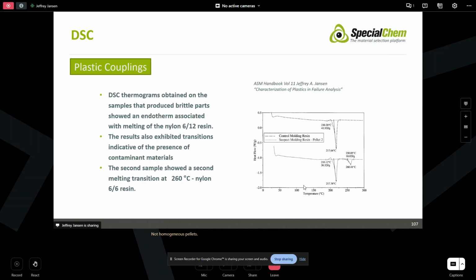We ran another one, and this time our nylon 612 was contaminated. That particular pellet was contaminated with nylon 6,6. So again, major amounts of contamination that are going to create problems. DSC did a great job of identifying that. FTIR really didn't identify that very well. DSC played a key role.